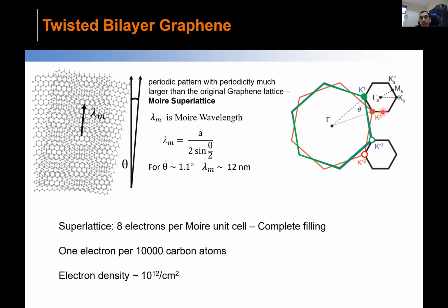Now you can calculate. Earlier, as I said, it was 4 electrons, but here there are 2 layers, so it will be 8 electrons per Moiré unit cell, and that corresponds to 1 electron per 10,000 carbon atoms, because your unit cell is quite big now, right? With lambda m, I'm talking about 12 nanometers. So if I fill this 8 electrons per unit cell, which is nothing but 1 electron per 10,000 carbon atoms, I can fill this new superlattice band.